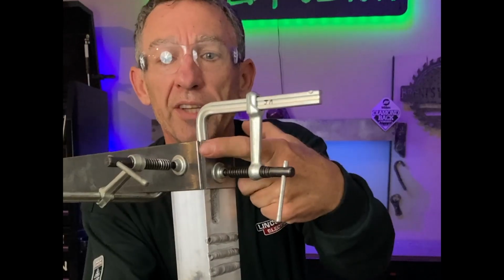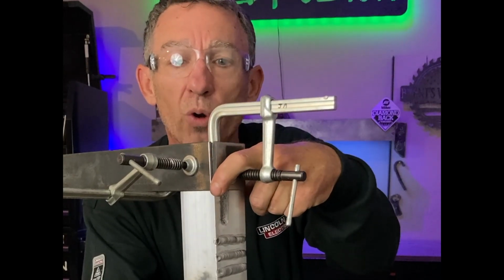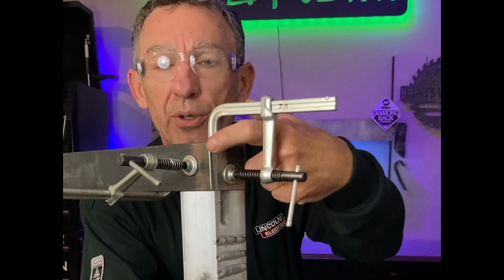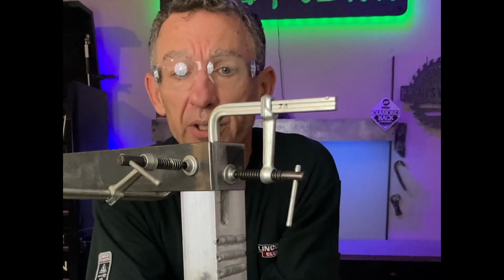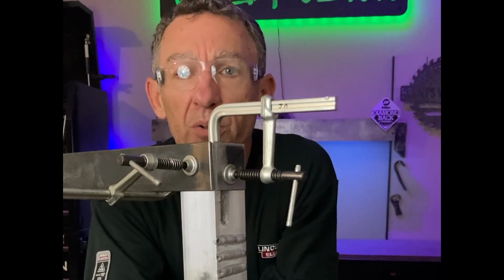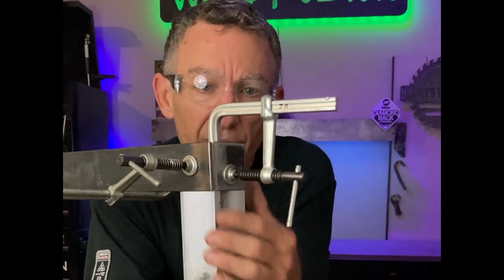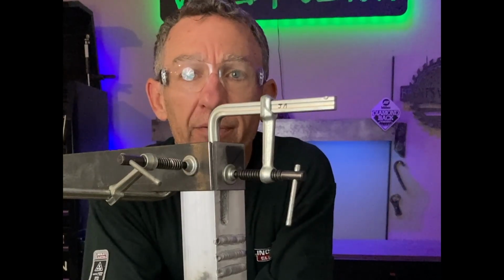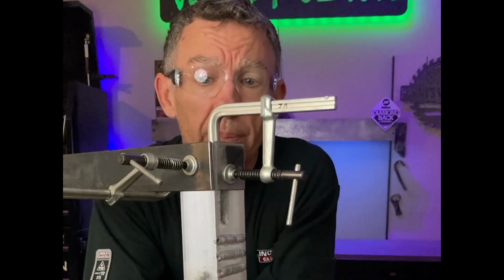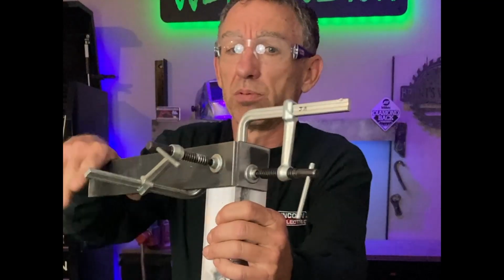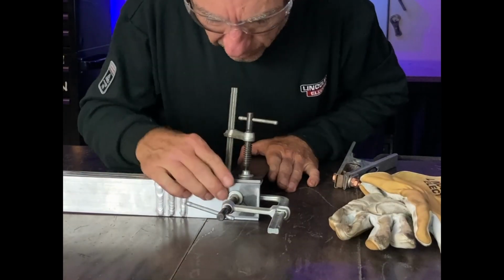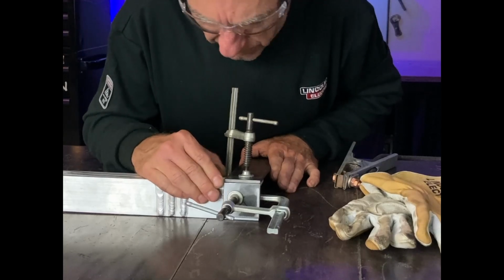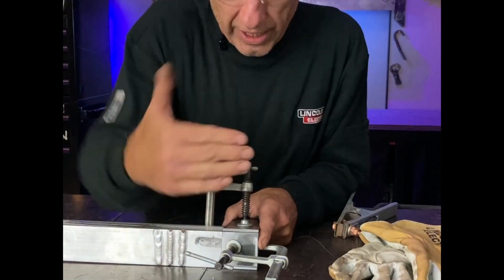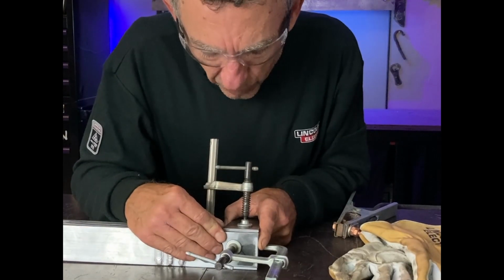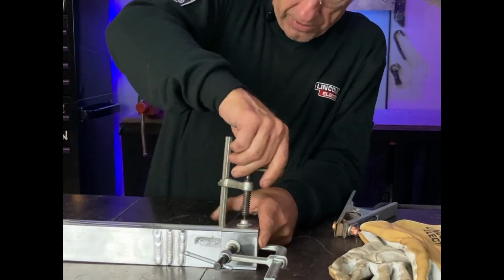We're going to end up with a joint that looks something like that. It's an open outside corner joint. We're not getting any overlap of the material. It gives us full access to the root of the material. And when I put this weld in there, if I can fill that joint in a single pass, we should have pretty much 100% joint penetration. At least that's what I'm hoping for. Let me check my final alignment here to make sure we got a straight weld going across. I'm trying to align it on the sides, and I'm trying to align it across the weld here. All right, I like where that is.